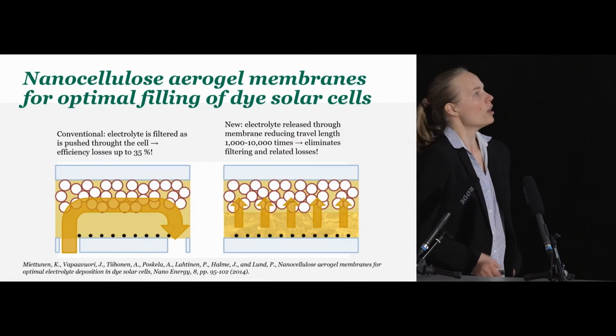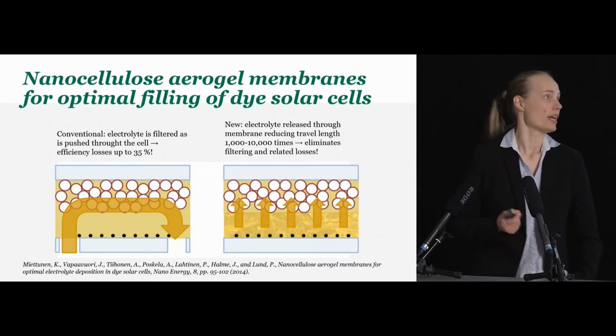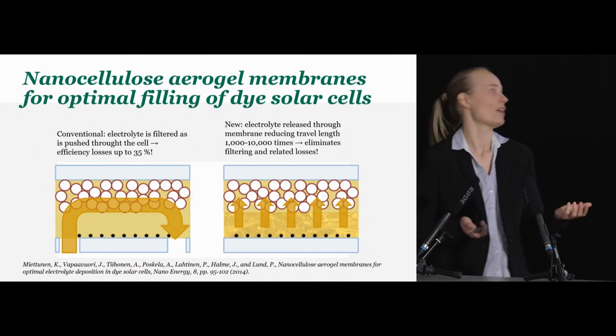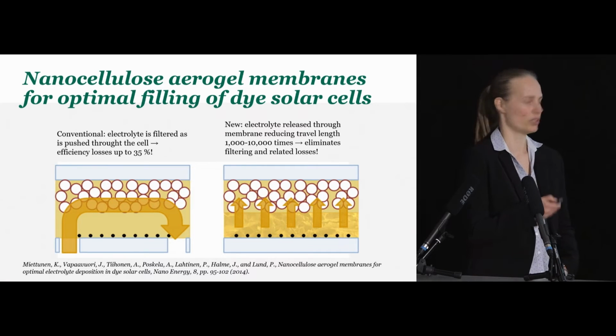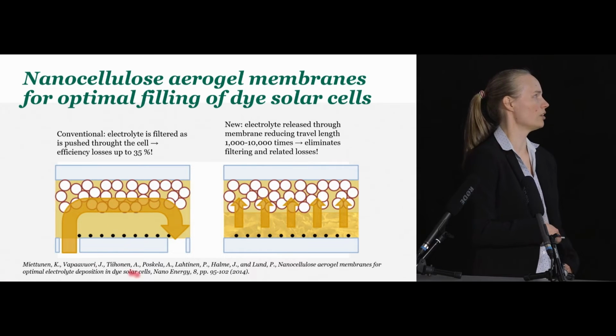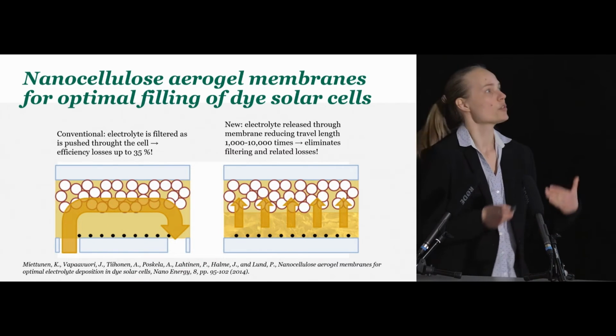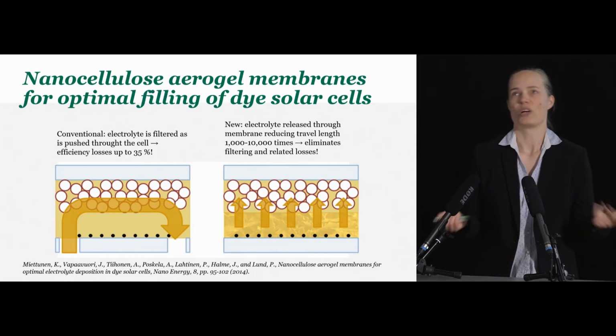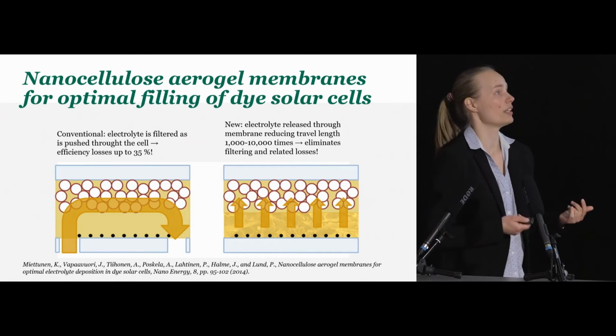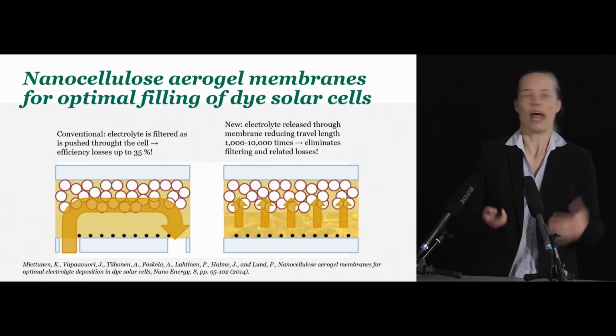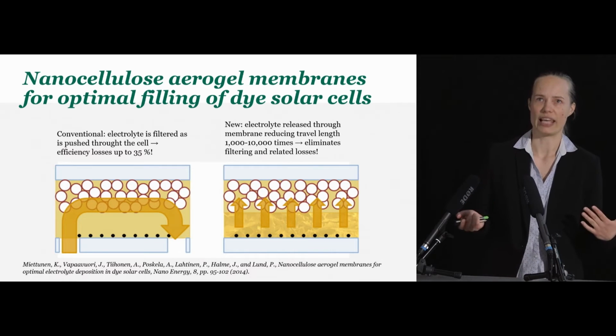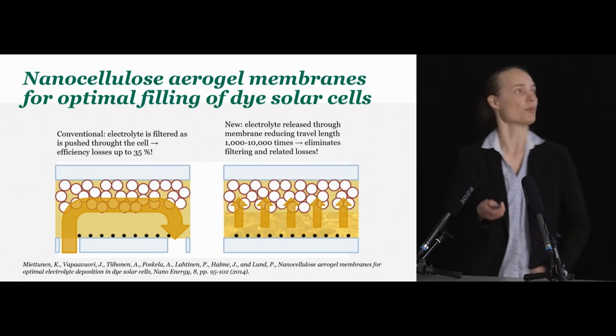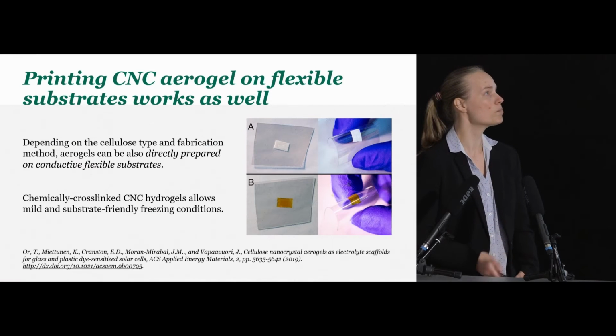So a few benefits that this strategy can achieve. First of all, we can eliminate one very common pathway for electrolyte leakage, since we don't need to use this type of holes on the counter electrode. But also, we can at the same time eliminate one common pathway for impurities to get into the solar cell. And thus, we can argue that this can again help to improve the lifetime of the device a little bit.